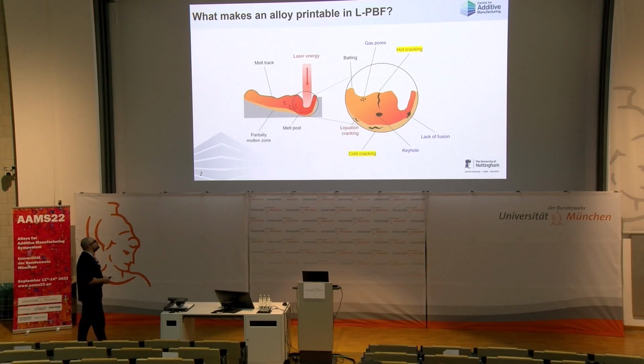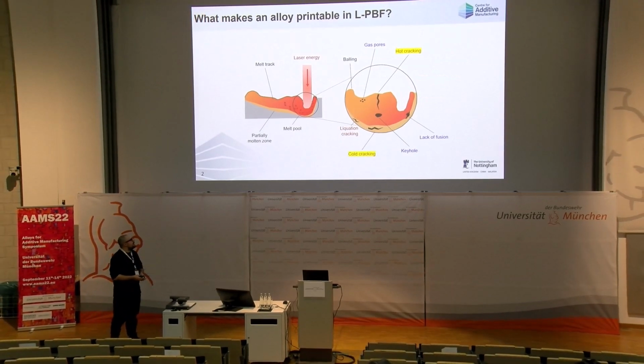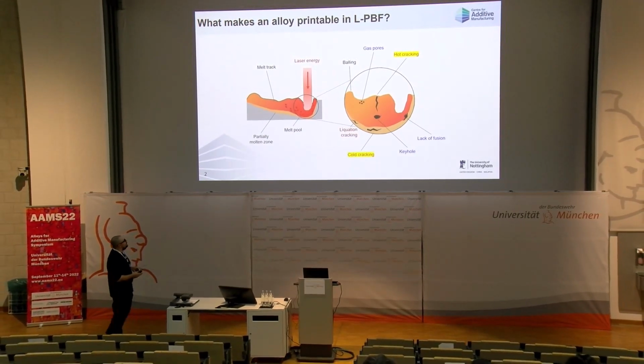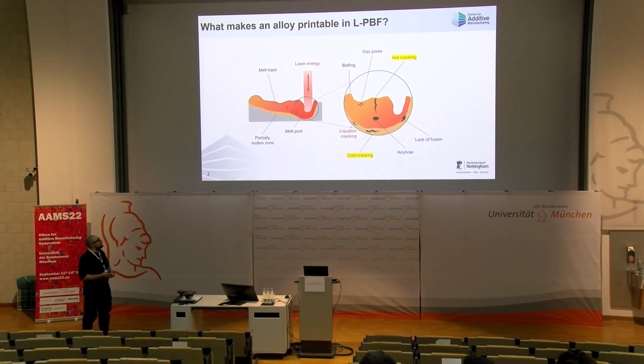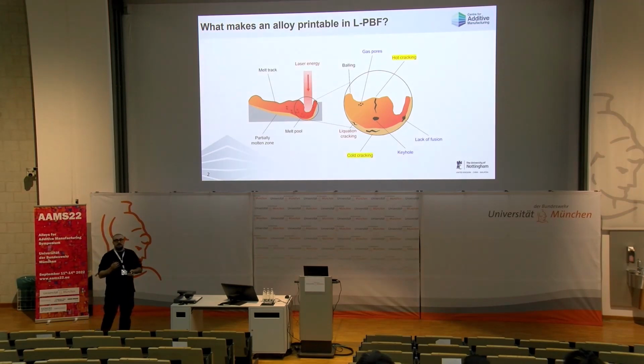When we are talking about printability in L-PBF, we refer to all kinds of phenomena that regard the interaction between a melted track, a substrate, partially melted zone, and also within the melted track itself, the behavior of the liquid, the mushy zone, and even a bit of evaporation with regard to keyholes. All these interactions may cause different effects in L-PBF, as we all know, which mainly can be subdivided into two classes. We have porosity and we have cracks.